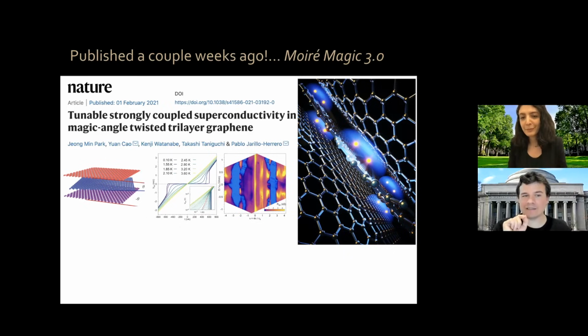But you're right that actually, especially when you have very small angles of rotation between, let's say, these two graphene sheets, the carbon atoms like to adjust locally and relax the structure locally, okay? So there is indeed lattice relaxation present there, so that the carbon lattices can accommodate more easily the preferred configuration. That lattice relaxation plays a fundamental role in the single particle gaps that isolate the flat band from the other remote bands. And having those flat bands isolated is very nice for its topological properties. So lattice relaxation plays a very important role.